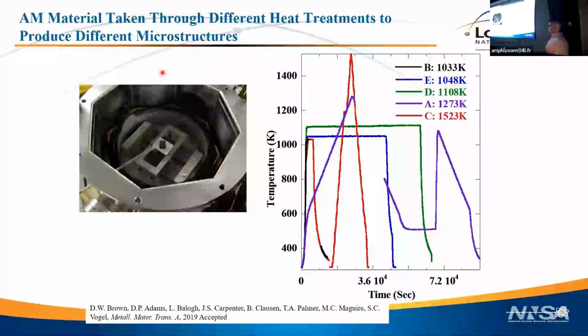And we went through a bunch of different heat treat processes. Here's the thermal profile that we did. This is an hour here, right? So that's 2 hours. And we collected neutron data while we're doing all this. So in the case of, for example, sample E, we heated up to 1048 K, so that's 800 C, which might be a reasonable heat treat temperature for steel. Held it there for about an hour and a half, and then cooled it.